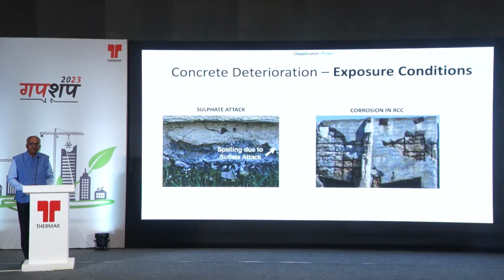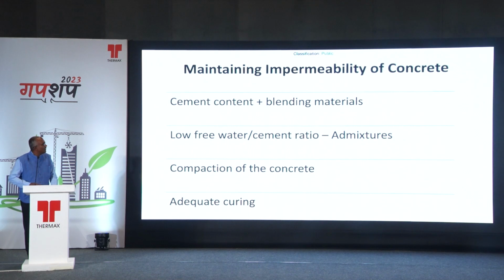You look at the deterioration mechanisms, sulfate attack or corrosion in RCC, both of which cause the concrete to expand in volume, maybe sometimes 5 to 6 times, and sometimes a short-term procedure step is being followed. That is, if there is a sulfate attack, why not recommend sulfate-resistant cement alone? But the problem with sulfate-resistant cement is that if you are not doing adequate analysis of soil, and if there is chloride, SRC cement is weak in resisting chloride. So things like that have to be kept in mind while we recommend a type of cement. SRC just means that it is good in resisting sulfate, but it is weak in resisting chloride because of the C3A content. So we have to keep that in mind when this kind of problem comes.